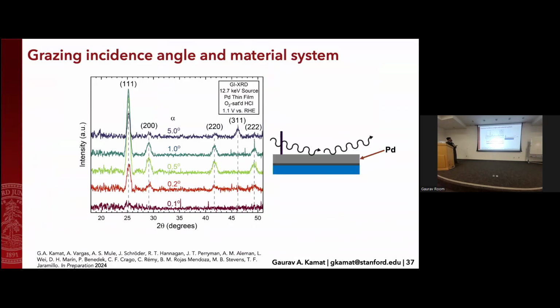One important thing is what angle you choose. I mentioned it's a grazing incidence technique, which means that you're putting these X-rays in at a very, very small angle in order to get just the surface region's signal. So if I choose an angle of, say, 5 degrees, I definitely get my signal from the sample, but I also get some other peaks that are coming from substrate layers and other things that are underneath. Not desirable because it's not as surface sensitive as we want.